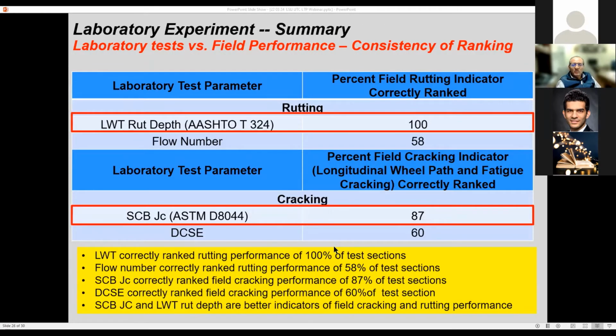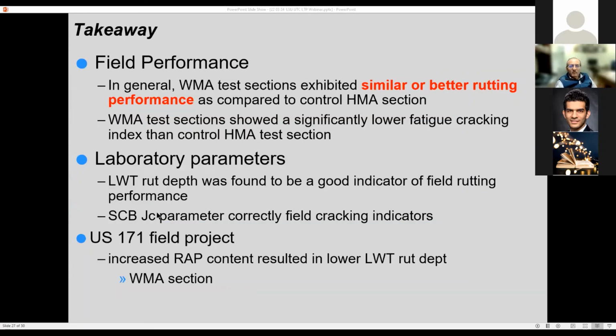So to put this in numbers, all of this tended to say that the ability of a laboratory test to correctly rank mixtures was 100% in terms of LWT and 87% in terms of SCB-JC for those test sites that we evaluated. That always gives you an idea of whether the laboratory test that is developed and used relates to field performance. So these are some of the technical data that can offer you a baseline for whatever mechanical test you want to use. The key takeaway, in summary, for this presentation is that we observed that WMA test sections did well when compared to HMA sections.